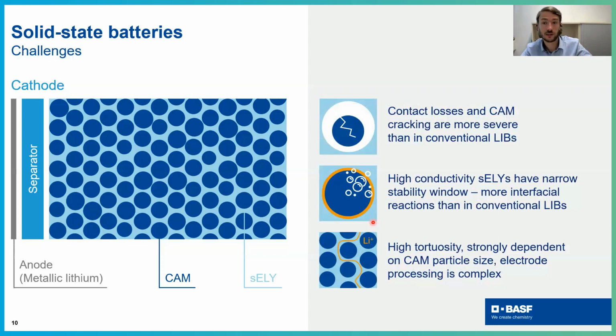And first, the challenge is mechanics of the solid state batteries. Here, what is typically happening, you have contact losses between cathode active material and your electrolyte. It happens because of volume changes of the material and also because of cracking. And another thing is that most of the high conductive solid electrolytes are actually not stable in the potential range you are operating typically. And you have actually more interfacial reactions than in conventional lithium-ion batteries.